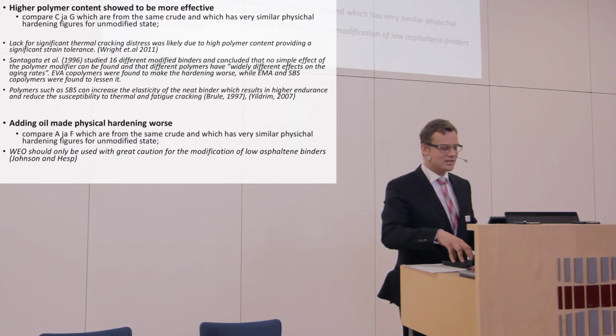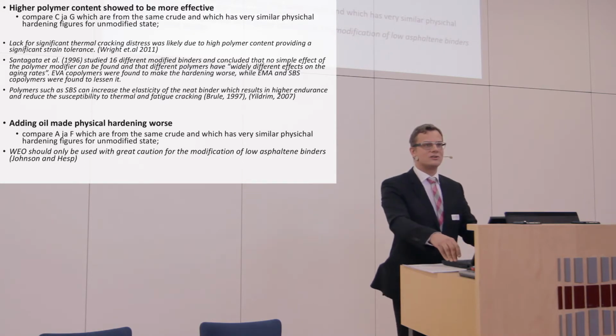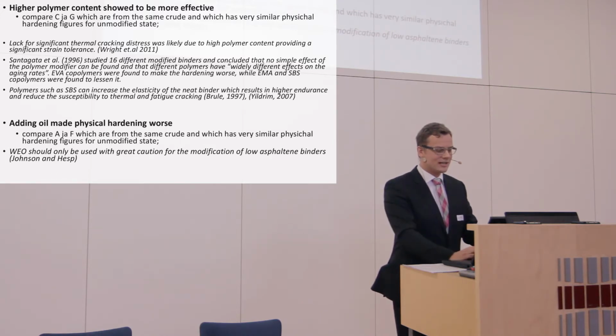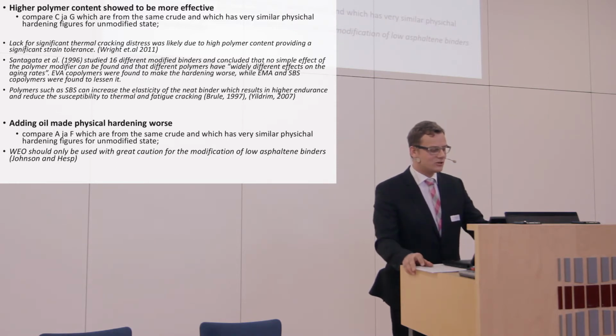So oil modification made physical hardening worse, and we can conclude from this that the literature is on the right track. Johnson and Hesp concluded that waste engine oil should only be used with great caution for modification of low asphaltene binders.